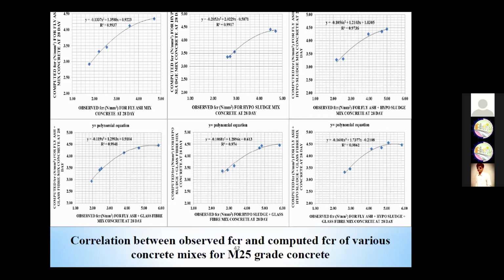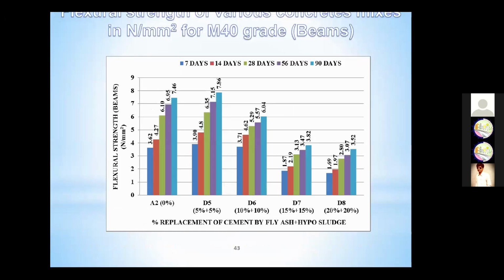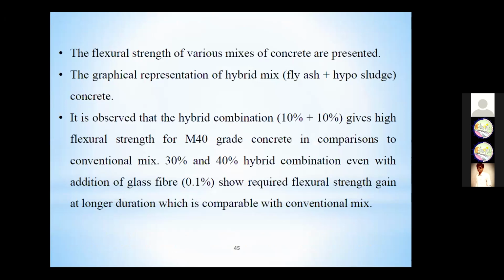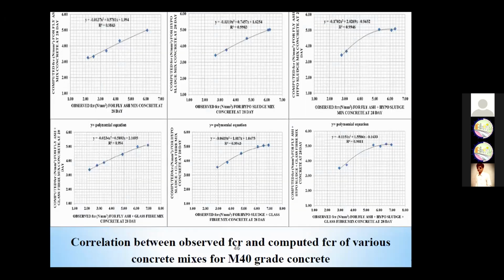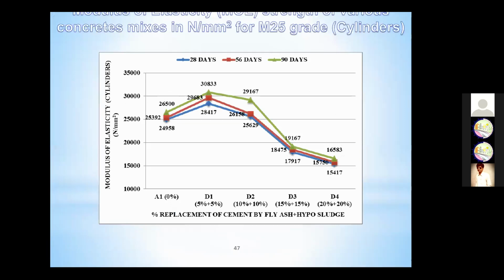Then for the M40 grade of concrete, we refer to it being nearer to 1, so the regression is good. So with the hybrid mix, without hybrid mix, addition of glass fiber in the hybrid mix, without hybrid mix, glass fiber concrete, all are concrete, but hybrid mix and the glass fiber give the excellent strength in the M25 grade of concrete and the M40 grade of concrete. Now same way we go for the flexural strength, the FCR, computed and observed, for the M40 grade of concrete. Same way we refer to the modulus of elasticity, cylinder strength, the D1, D2.